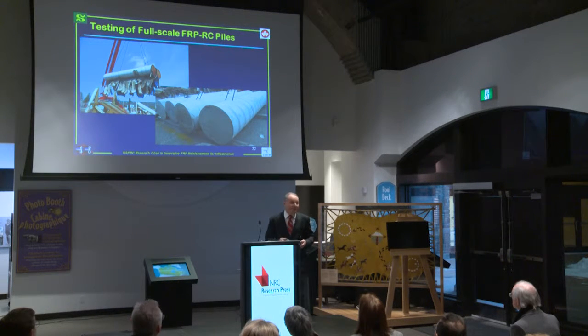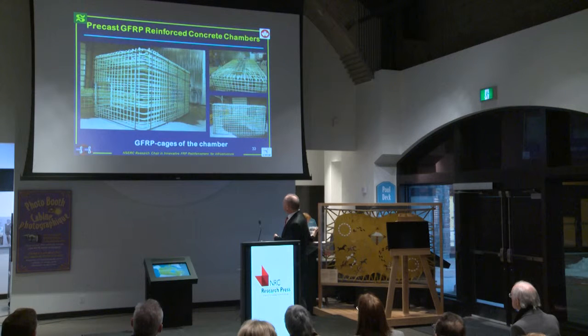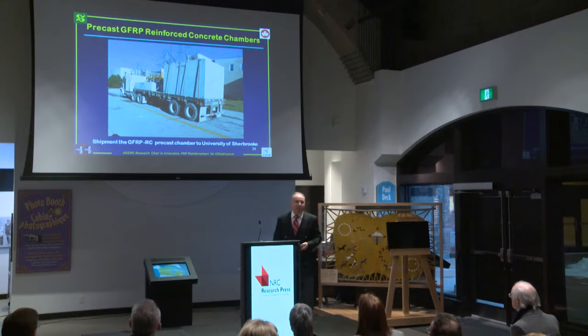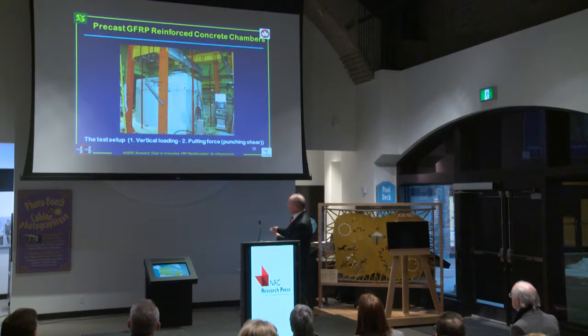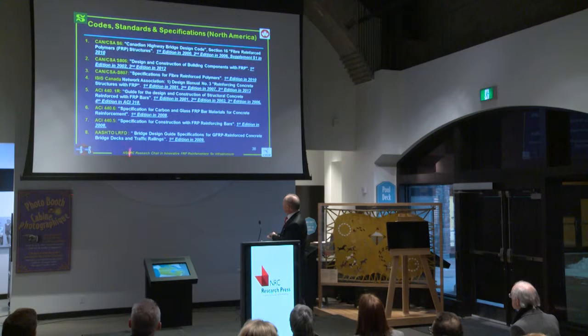We also built piles and piers using this material, and we simulated them under earthquake and cyclic loading. This is to develop equations and a design methodology for using this material. As you can see here, this is a current project that I have with Hydro-Québec. It's about $2.5 million for 3 years, looking to implement all this in these chambers. They are fabricated by a precaster and brought to my lab for testing, because Hydro-Québec would like to change all their designs made with steel to FRP, because they will gain in terms of long-term durability and so on. This is the whole structure being tested in the lab.